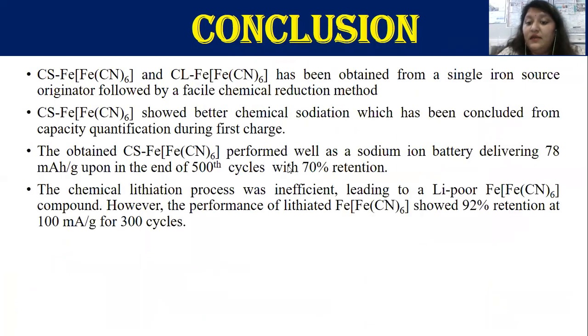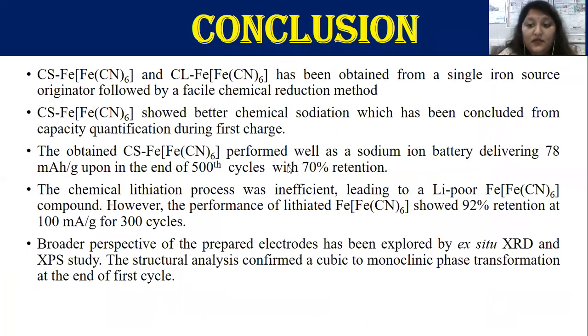So, as a conclusion, chemically sodiated PBA and chemically lithiated PBA have been obtained from a single iron source, followed by a facile low temperature and rapid sodiation and lithiation process. The proposed chemically sodiated FeFeCN6 showed better chemical sodiation, with sodium rich compound formation, which has been concluded from capacity quantification during the first charge.